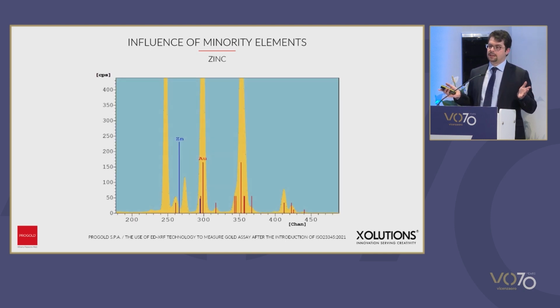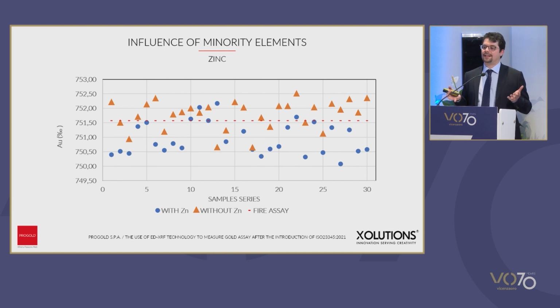And then we wanted to focus on one specific element, zinc. Why zinc? Because if we look at the absorption spectrum, we see that there is a partial overlapping of zinc with one of the secondary peaks of gold, something that does not happen with other elements such as palladium and copper. So there could be an interference between zinc and gold. And for that reason, we decided to carry out a series of analyses where we checked what happened if we declared to the instrument that zinc was present in the same quantity as it is normally present in these alloys, or if we ignored and did not declare the presence of zinc, thus avoiding that the machine would force the content of zinc.